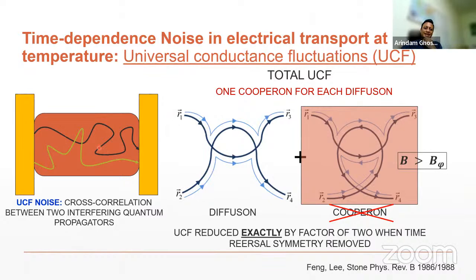Now imagine there are these regions where the two paths intersect and interfere. Okay, that leads to interference effect, and the same idea leads to weak localization as well. But I'm going to go one step beyond weak localization. This is called universal conductance fluctuations. So we have to consider two paths. Then imagine this situation where these two paths interfere by crossing each other. Okay. Now, when they cross each other, you will have two different ways of crossing.